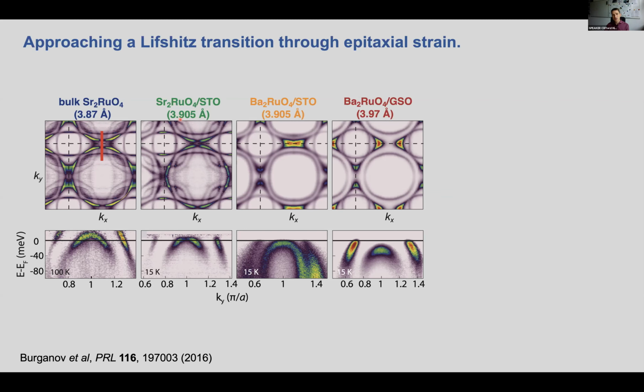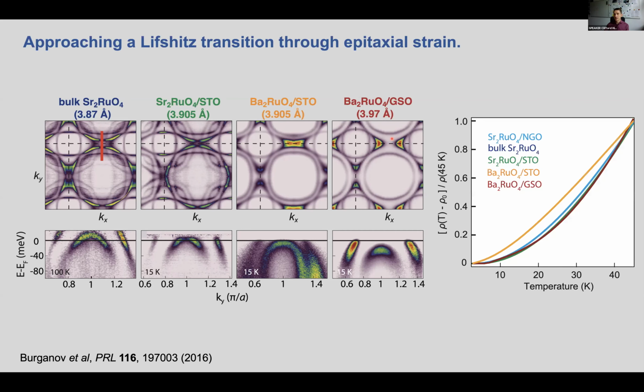When the lattice constant is expanded by growing it on a strontium titanate substrate, we're now much closer. When they switch to barium ruthenate, which for thin films has nearly the same electronic structure, they are right at the Lifshitz transition. And now when they expand the lattice constant further, they have clearly gone beyond it.